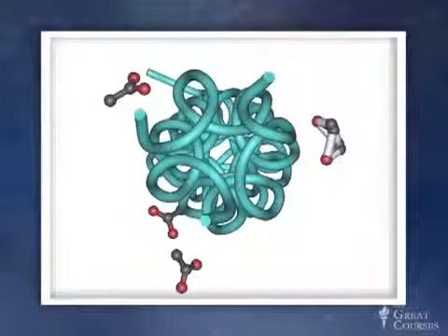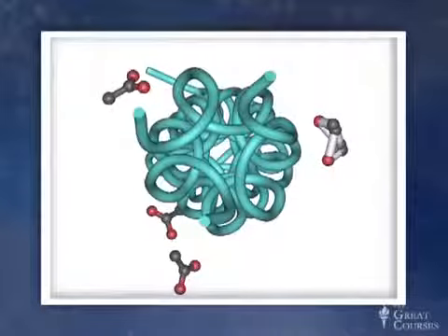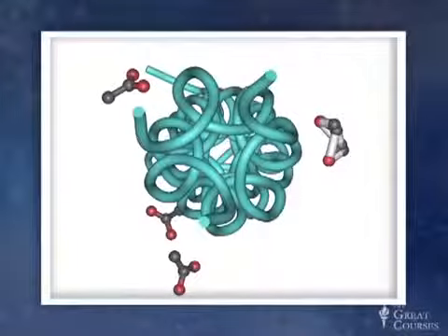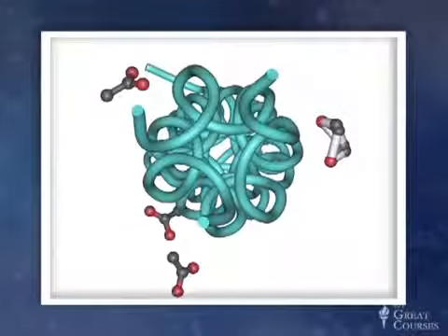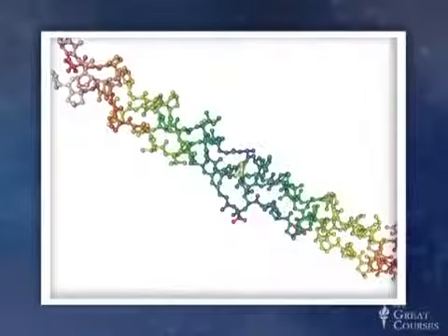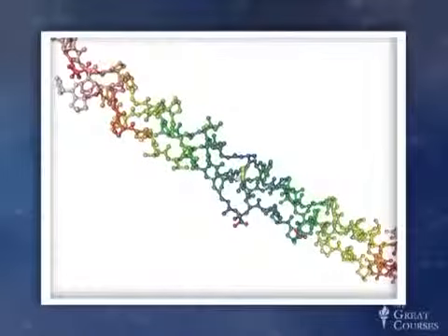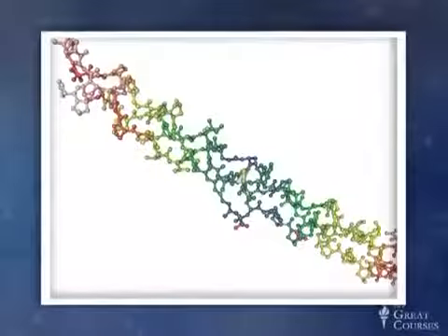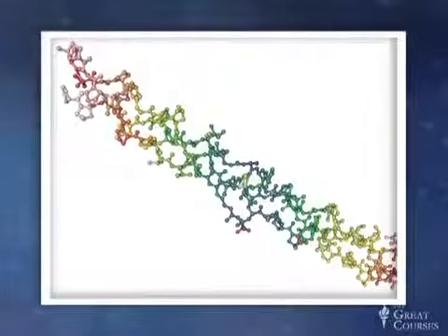It has a very interesting structure, so rather than being variable, it's quite constant, and it always exists as a triple helical structure about 1.5 nanometers wide and 300 nanometers long. These triple helices of collagen are wound into tough bundles. They can be hundreds of nanometers thick, and they provide a guide that can tell cells where to grow.